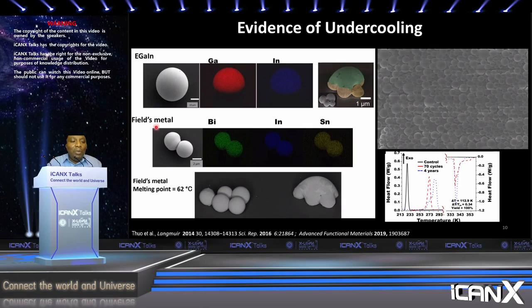Then when we did the same experiment with Field's metal, which is now a ternary alloy, we found that we get very smooth particles and the distribution of the components is even, meaning we have a solution in the core. If these had solidified, we would see spinodal decomposition. We would see separation of the different components. And of course, when we take that alloy and we mill it, we get almost a similar structure as we found with eutectic gallium indium. And as a further proof, we see that,